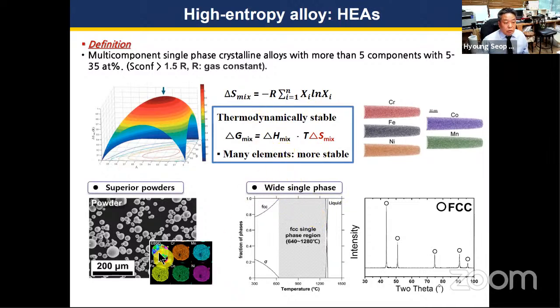HEA has very good powder and liquid flow properties because it has low melting temperatures, it's multi-materials, and it has a very wide single phase region. So these two characteristics, low melting temperature and wide single phase range, are ideal for additive manufacturing. Plus, various elements can induce cell boundary segregation that results in superior mechanical properties in AM parts. So high entropy alloys are excellent candidates for additive manufacturing material.